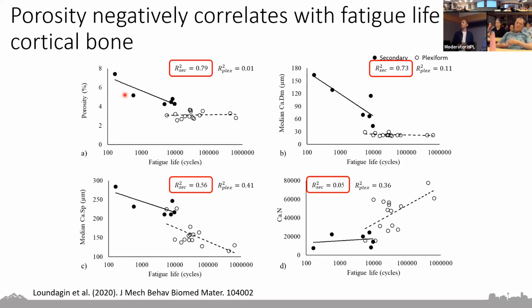This porosity is largely going to be attributed to void space created by vascular canals in the cortical bone. So it's going to be a function of both the size of the canals as well as the number of canals present in the bone. Some subsequent work found that this porosity led to a decreased fatigue life, more so because of the size of the canals rather than the number of canals present. You can see the high correlation here with the size of the canals. And then some other work from our group developed micro-CT based finite element models where we were able to quantify stress concentration volume. We found this metric to be a much better predictor of fatigue life than either nominal stress or strain.